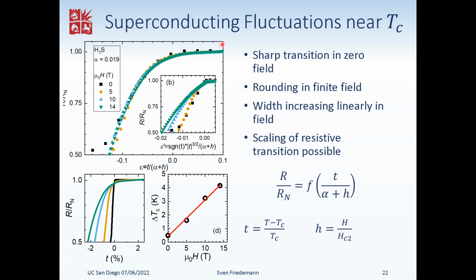So it suggests that we do have some universal behavior, some temperature over field scaling here close to the transition. Usually this is associated with flux movement, vortex movement. But as I said, traditionally it has been derived in theory that it should go as T to the 3/2 divided by field. We don't observe this, so that is an open question, what that might mean for the superconductivity here.